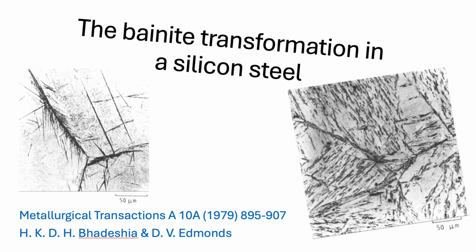They did, and the shape of it, the morphology, was telling. It wasn't smooth plates growing steadily. It was this interwoven, almost feathery branching structure. Like fingers interlacing? Sort of, yeah. Very complex. And that kind of shape is really hard to explain if it's growing by slow, steady diffusion across ledges on the interface. It doesn't sound like orderly growth. Not at all. It looked much more like it formed through lots of little rapid bursts, like tiny martensitic jumps, creating small subunits that then link up. Okay, the shape suggests something rapid and maybe shear-like.